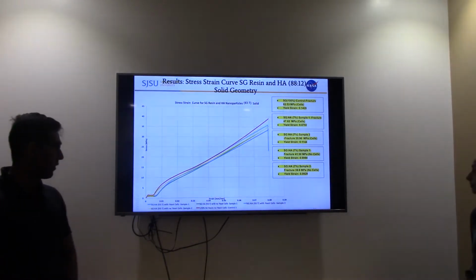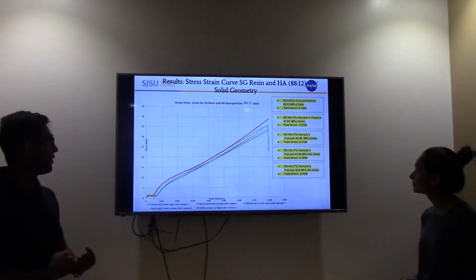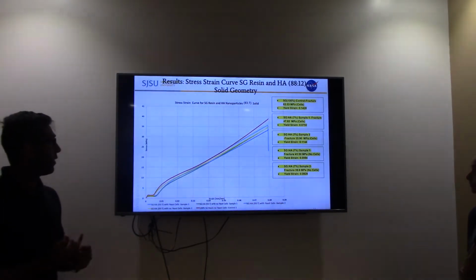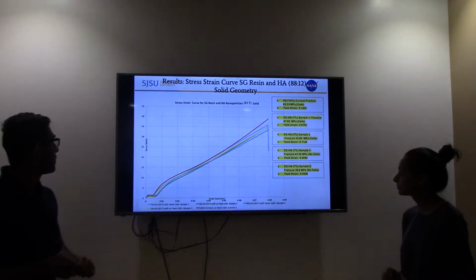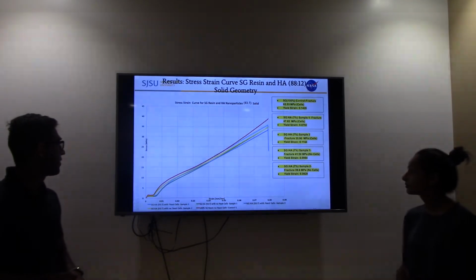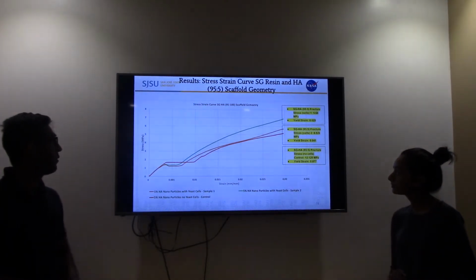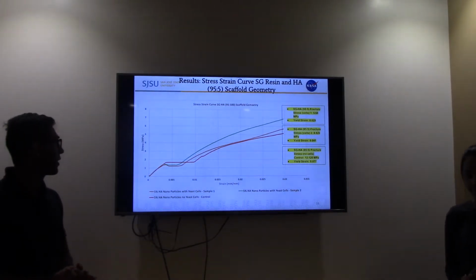And here are the results. The red line is the SG resin without any HA, so that was our control. As you can see, the HA nanoparticle specimens were weaker than the control, about 3 megapascals lower in tensile stress. And here we have the scaffold test results, where each of them were not significantly different based on with or without cells, but they were weaker than the solid geometry, which we expected.